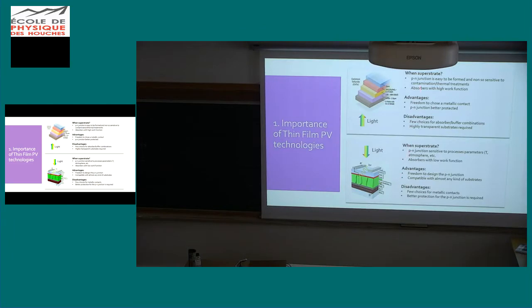There are two possible configurations of a thin film solar cell. What we call superstrate, this is the substrate. In a thin film solar cell, we always need a substrate, because of course, if you are speaking about 1-2 microns of material, it is mechanically fully unstable. So you need to support this very thin layer on top of some mechanically robust substrate. The universal one is, of course, glass. So if you illuminate your device from this substrate, then you are in the superstrate case.